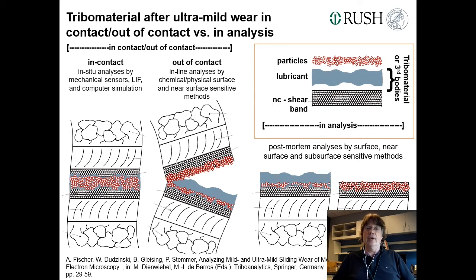And now if you separate both contacts, you might get this sample or you might get this sample. So if you only analyze one, you do not even get 50% of the entire story. So you always have to analyze both surfaces and see what's going on, because both in combination, if you do the separation process correct and do not do immediate cleaning afterwards, might tell you what has been this stuff in between, what we call tribal material, that allows for the accommodation of the extreme shear rates in such a contact and not generate large wear rates.